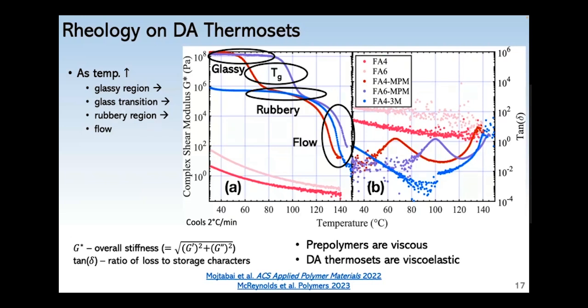I also performed dynamic rheometry characterization on the same materials. And in these plots on the left, I have plotted G star, the overall stiffness, and on the right, tan delta, or your ratio of loss to storage character, and this is against temperature.